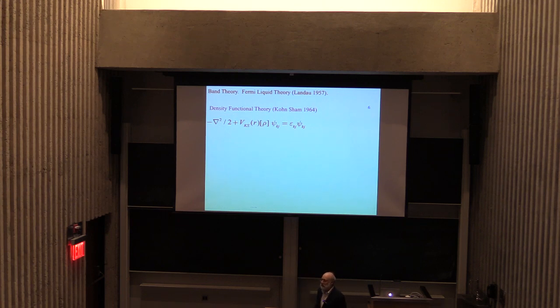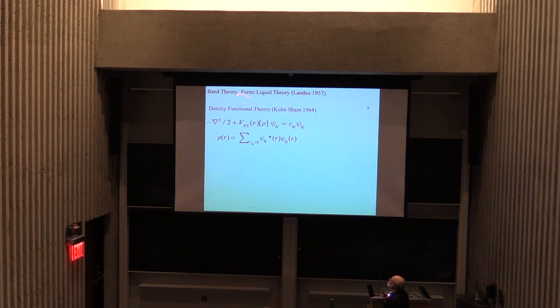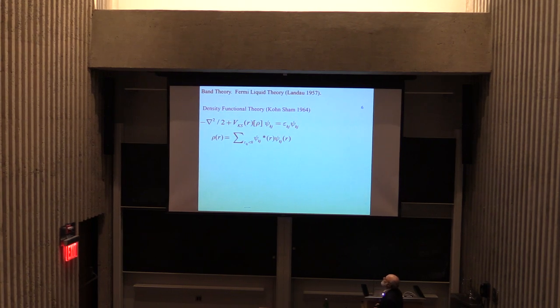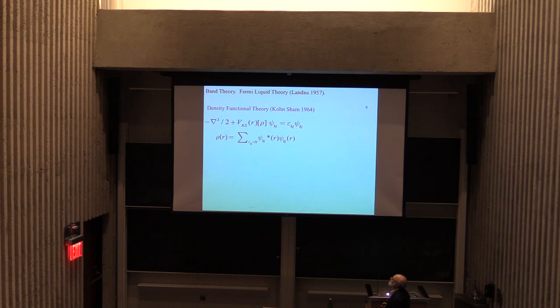And I'll define now what I mean by a weakly correlated material. What Landau Fermi liquid theory says is that even though in every material all the electrons interact with the Coulomb interactions in a solid, so we always start from an interacting system, there are cases where, if we look at the material on a relatively low energy scale, the interactions normalize essentially to zero. So if I look at the problem very close to the Fermi surface, then the weakly correlated materials are those for which the interactions really fade away at low energies. And the density functional theory gives us a prescription for computing the excitations in those materials. It's an idea that you solve something like a Schrödinger-like equation in a self-consistent potential, something like Hartree-Fock, but a little bit more intelligent than Hartree-Fock.